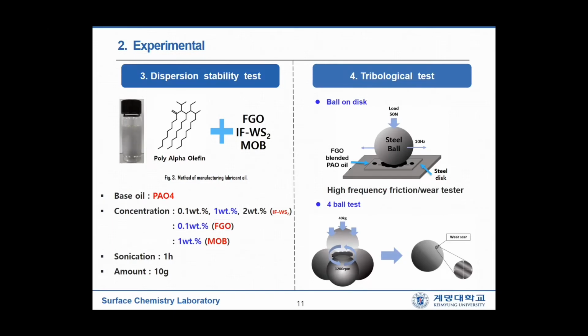This is a dispersion stability test. Functionalized graphene oxide with different sizes of alkyl chains are dispersed in base oil. PAO4 is used as the base oil. The concentration of IF-WS2 in base oil is varied to 0.1 weight%, 1 weight%, and 2 weight%.